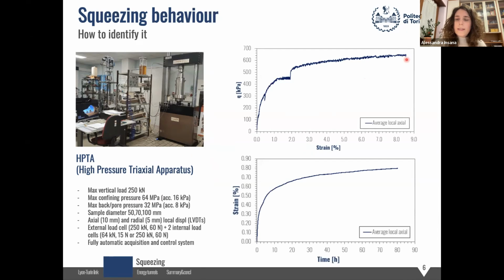And here you can see some examples of creep tests, triaxial creep tests that we have performed. So the creep curve corresponding to this deviatoric stress can be seen below. And we can also appreciate the so-called apparent consolidation phenomenon. That is that after a creep phase, when we reload the sample, the stiffness of the sample is much higher, but then it goes back to the stiffness it had before the creep test.